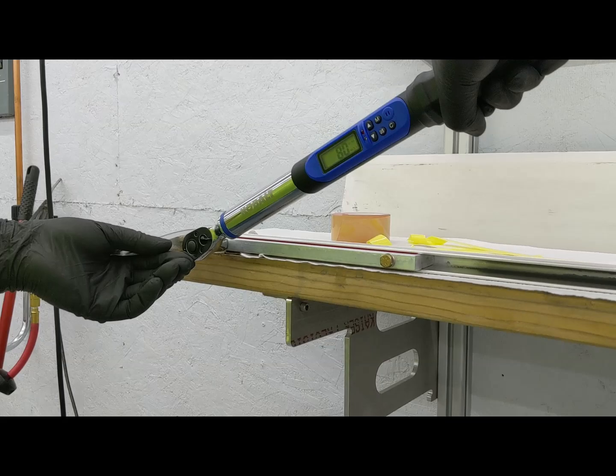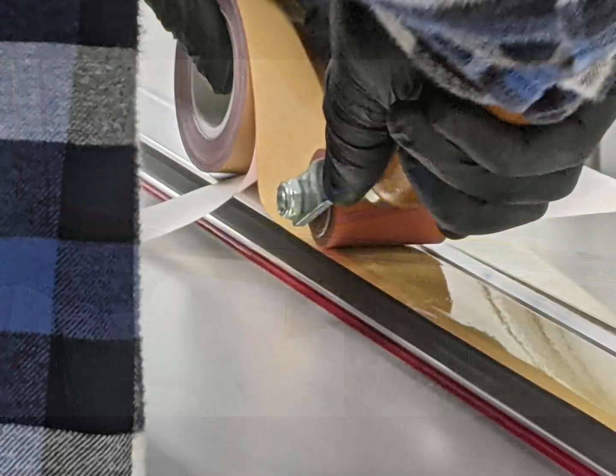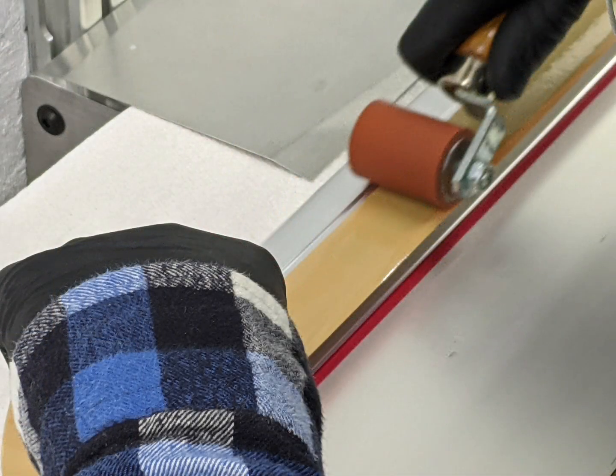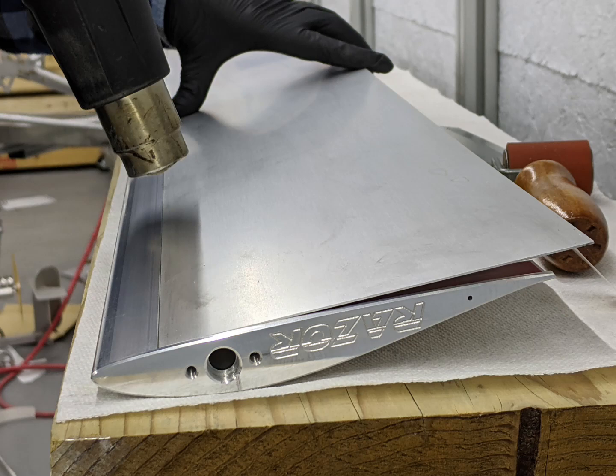Once the internal components are in place, we can start on applying the adhesive for securing the top and bottom skins. The adhesive is rolled to remove any trapped air bubbles before the backing material is removed from the adhesive and the skins are applied. A small amount of heat helps the initial tack before being transferred to the curing oven. All these components are tracked via lot numbers as well as the adhesive for every set of blades.